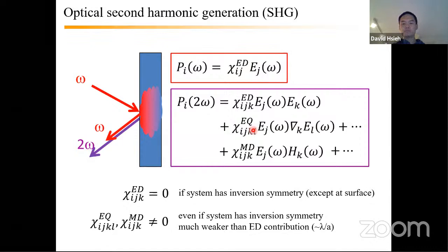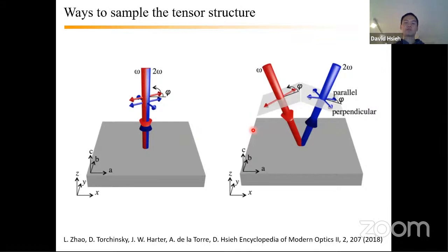I want to say a few words about the technique. So how do you go about sampling the tensor structure of, let's say, an SHG tensor? I'll talk about that before I go into the details of how we distinguish between the different processes. Technically, maybe the simplest way is just to come in at normal incidence to a sample. So your k vector is parallel to the surface normal. And you can measure the intensity of the reflected second harmonic light as a function of your incident light polarization and outgoing light polarization. Now this is commonly employed and is technically straightforward. However, you can tell from the geometry that there are limitations to this technique, namely that there's no field component parallel to the Z direction. They're all in plane, and so you fail to pick up a lot of tensor elements that involve a Z component.